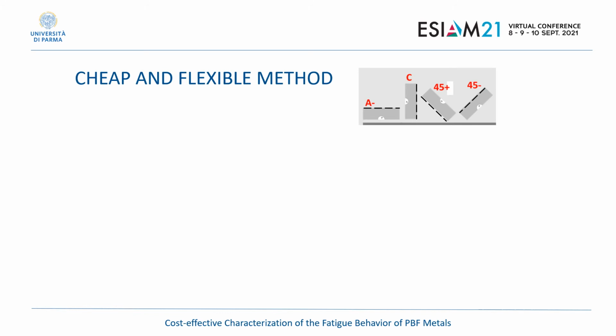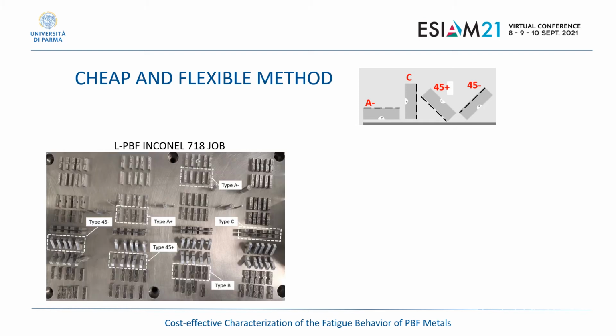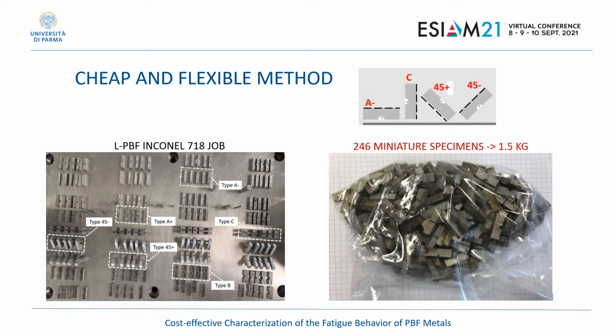The method that we propose is not only cheap, but it's also flexible. According to this scheme, we can test in fatigue different surface orientations. Here we can see the build that has been developed, where you can see a large number of Inconel specimens oriented in different directions. The total of 246 miniature specimens amounted to only 1.5 kilograms of material in the end. So it's really cost effective.